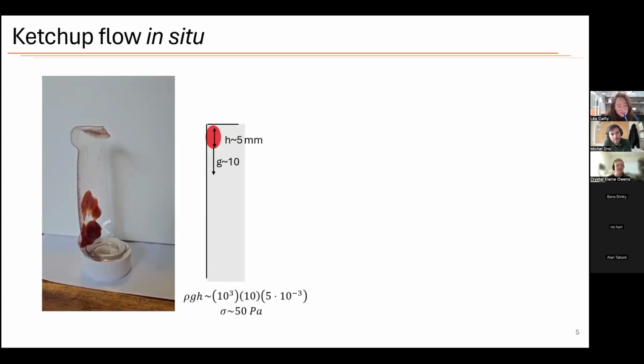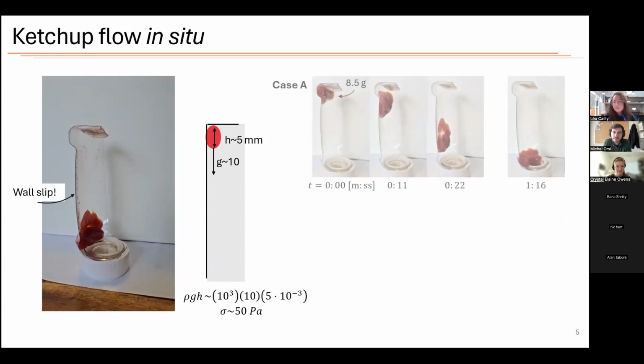So maybe this is something like ketchup under a controlled stress experiment of maybe 50 pascals or so. And so it also clearly experiences wall slip. And so this is something we might say is one case of what happens when you have ketchup you're trying to get out of the bottle. And this is probably one of the best case scenarios because everything kind of comes out smoothly, but it does take quite a while.